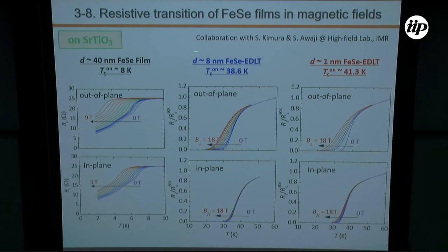Finally, I would like to show you the upper critical field of these systems. These figures show the temperature dependence of the resistive transition in the magnetic field for the 40 nanometer, 8 nanometer, and 1 nanometer iron selenide samples for the out-of-plane and in-plane configurations. In the case of 40 nanometers with the bulk TC, the width of the resistive transition is almost the same order, with an anisotropic parameter of almost 2. But on the other hand, in the thin regions, for these two samples, the transition width is very anisotropic. And you can notice that in parallel conditions, the transition width is not so different between the two thicknesses, implying that the upper critical field is not determined by the thickness only.